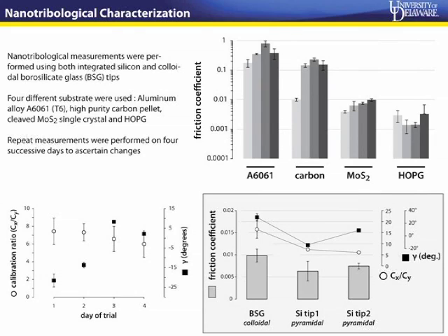The interesting thing again is your friction is more or less close, presumably slightly higher here because of maybe adhesion, because of the larger radius of the probe. But the really interesting thing is that your CX/CY ratios and the gammas are much higher for the colloidal probe. Scales are up here, and you can imagine because of the improper alignment of the probe with respect to the shear center of the cantilever, of course you're going to get a higher value of CX and CY, but you're also going to get fairly higher values of the misalignment.